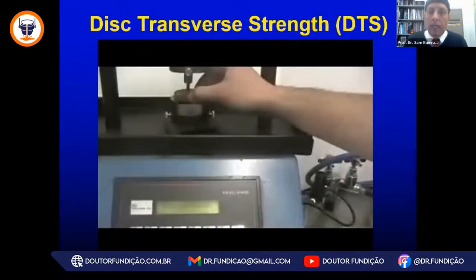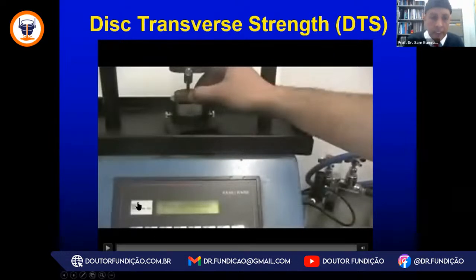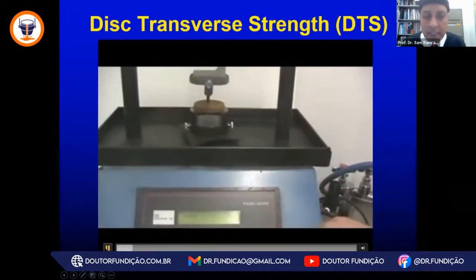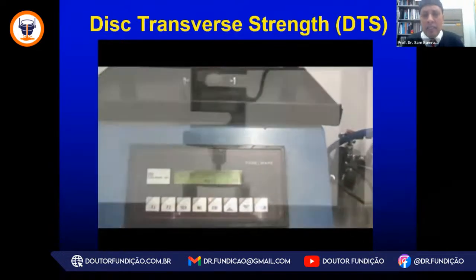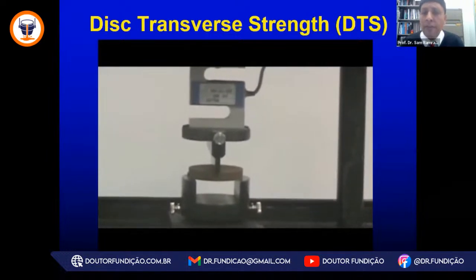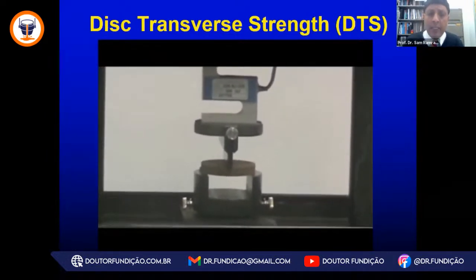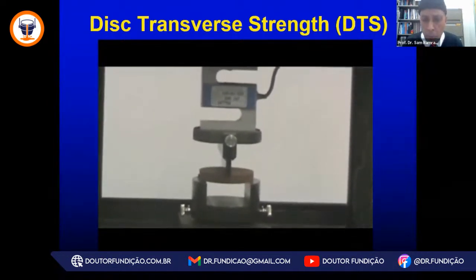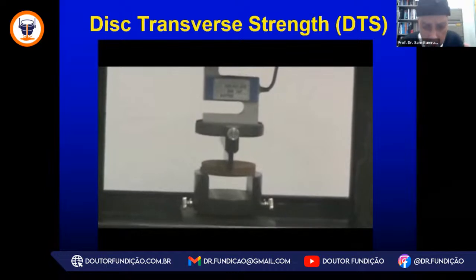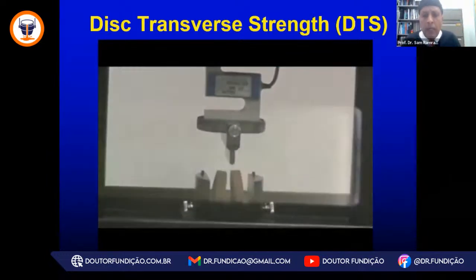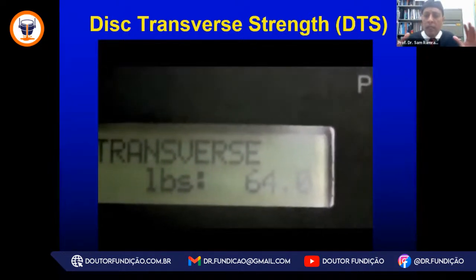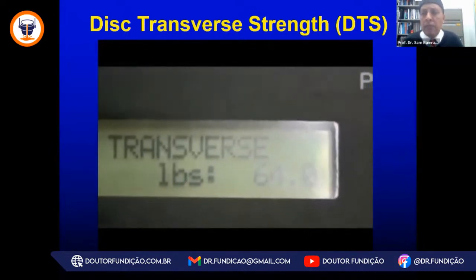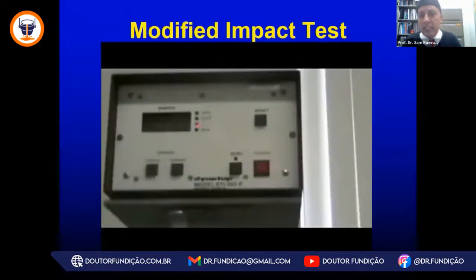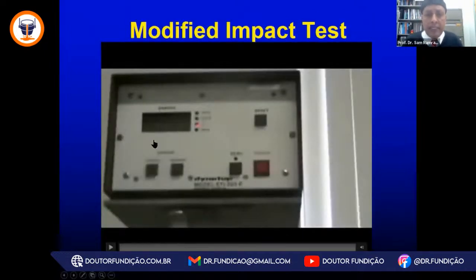The disc shape strength test is an AFS standard for the disc shape specimen, and this particular test is just a mechanical test. We don't like this mechanical test very much because very few molds and cores fail in this compressive shear mode. Again, what I'm suggesting here is a mold and core that we use in the casting process. They do not experience compressive shear. So for a mechanical test, the new standardized test is the retained strength test, which is an impact test.